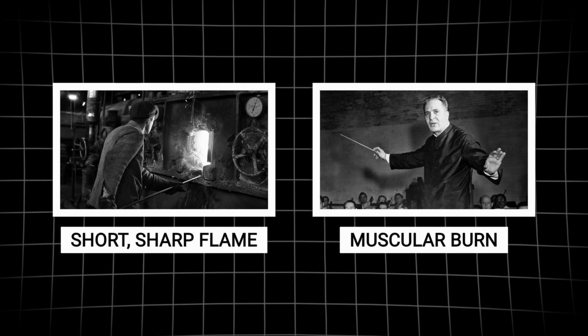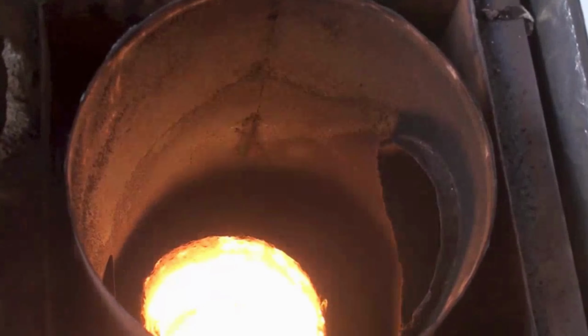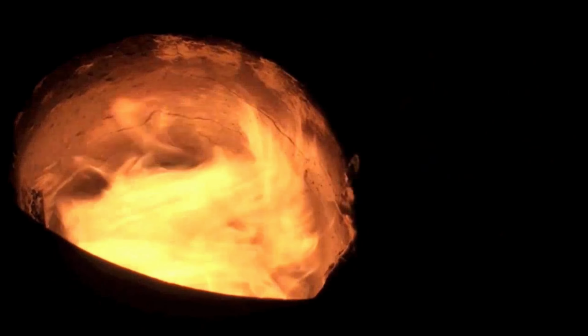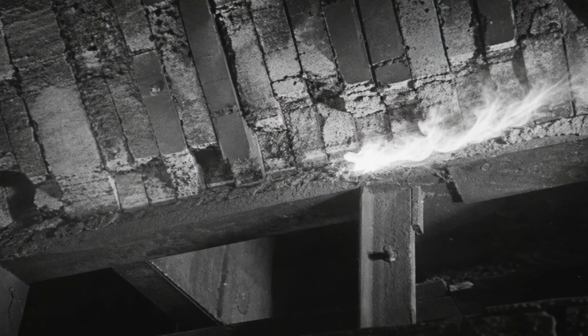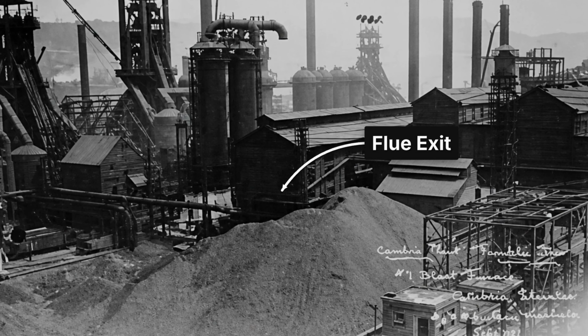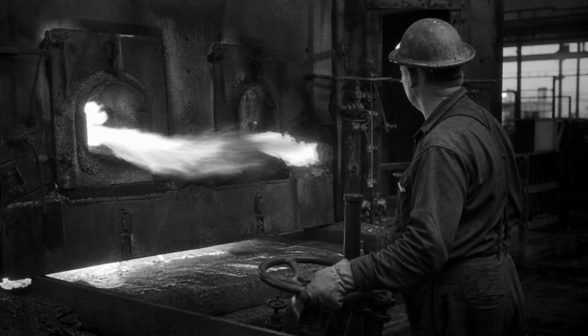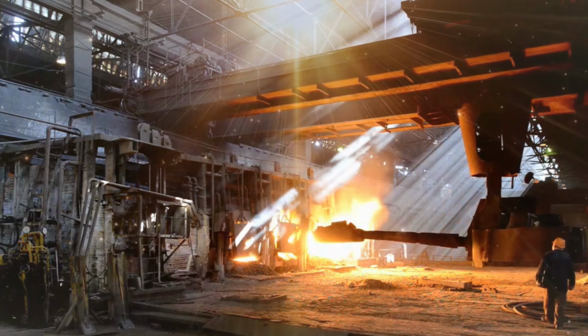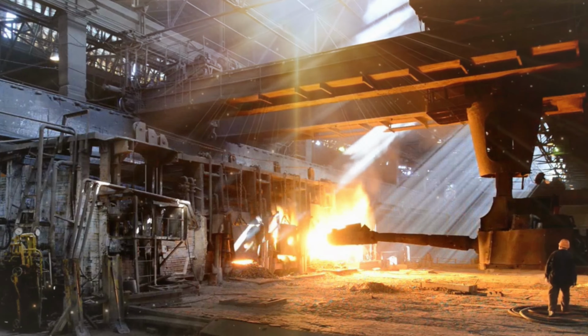Number 4. Reading the flame. An open hearth furnace burned gas or oil in a great swirling flame above the steel, and the melter tuned that flame the way a conductor tunes an orchestra. Too much air, and the flame ran short, sharp, and white, hot but wasteful, eating the roof brick. Too much fuel, and it ran long, lazy, and smoky, licking heat uselessly out the flues. The perfect flame had a color and a body the melter knew on sight. Luminous, muscular, sweeping down to brush the bath itself.